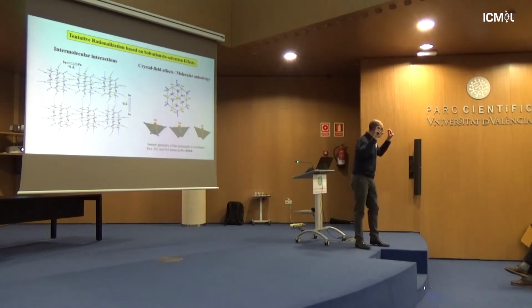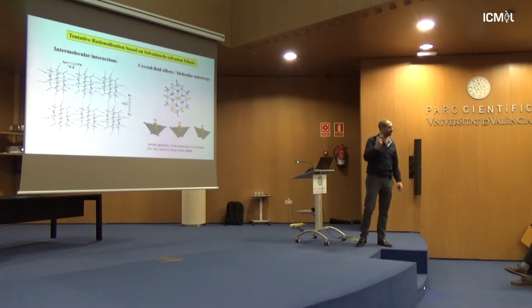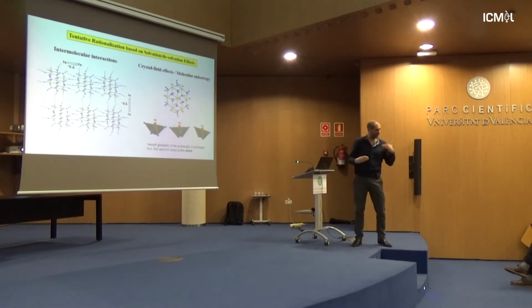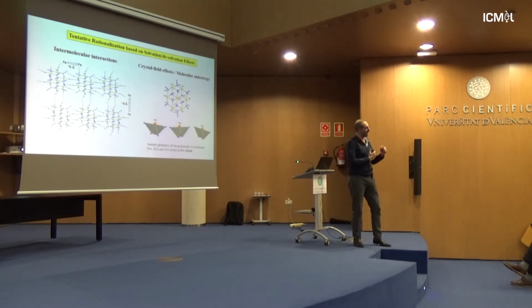In a hypothetical structure, I don't have a crystal structure of the dried compound because the crystals do not diffract in the dried form. But in that hypothetical structure, if you perform SHAPE calculations, you find out that the iron centers have a seesaw geometry.